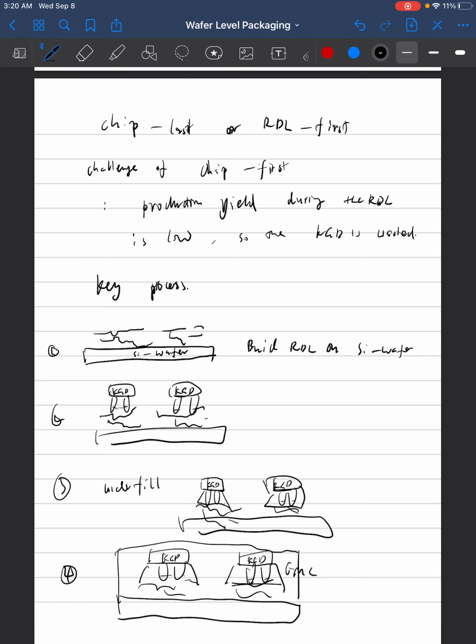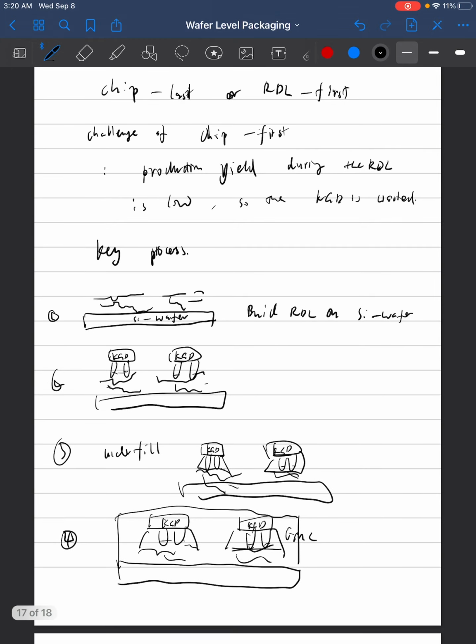First, we build the RDL layers on a silicon wafer or some other kind of carrier, a glass carrier wafer with certain sacrificial layers, so that in the last step we can remove this layer, either the silicon wafer or glass wafer, using the laser debonding technique. We build the redistribution layer using the standard process: spin coat photoresist, use a stepper to develop and etch in photolithography, then deposit metals, and we can fabricate the RDL layers.